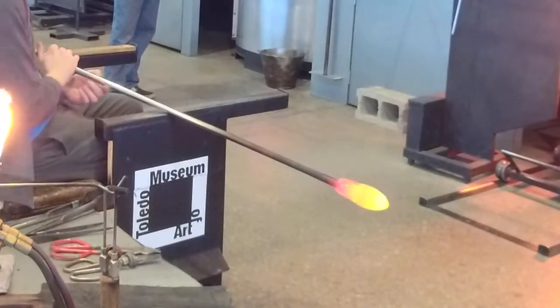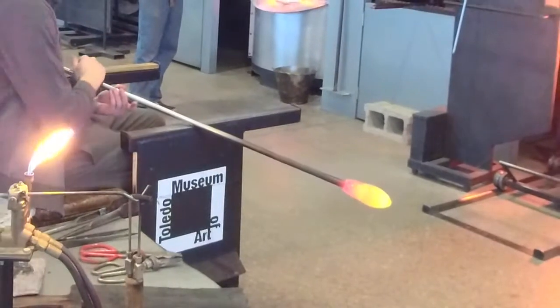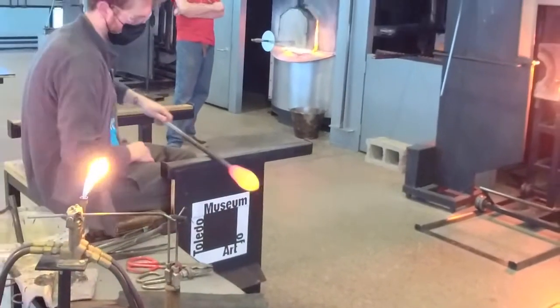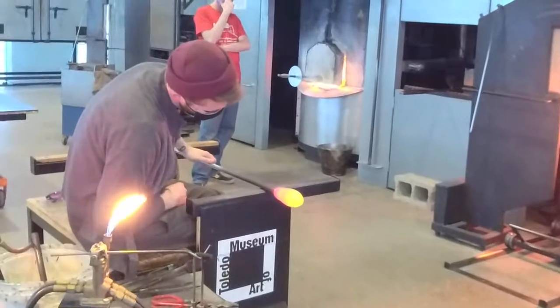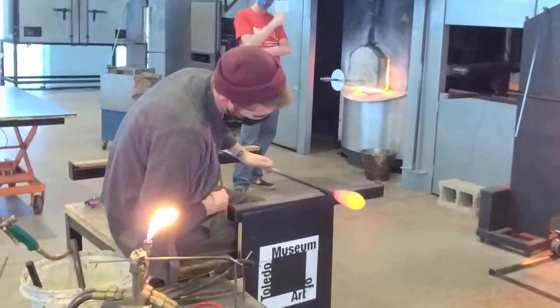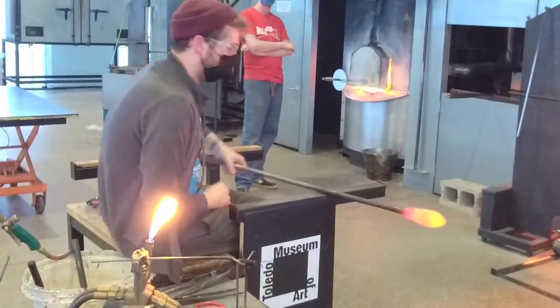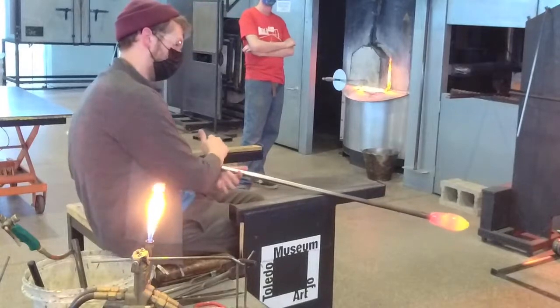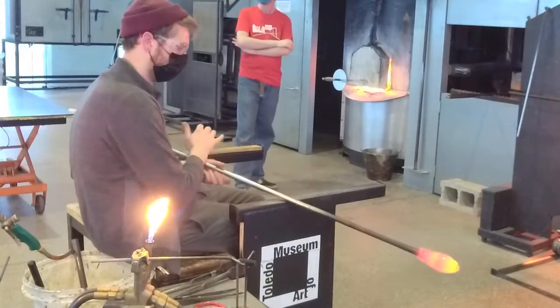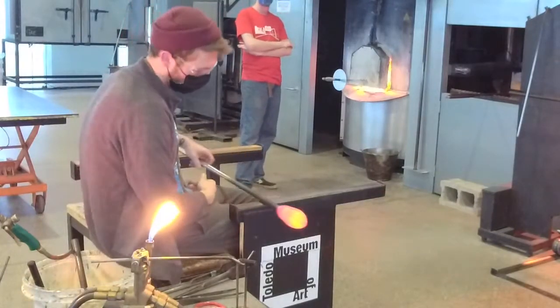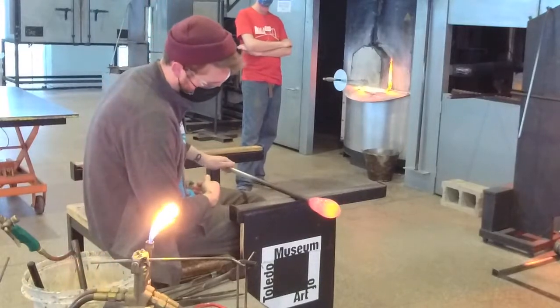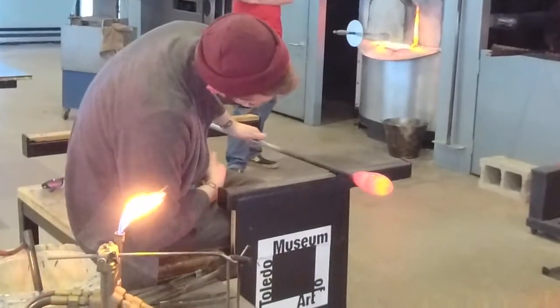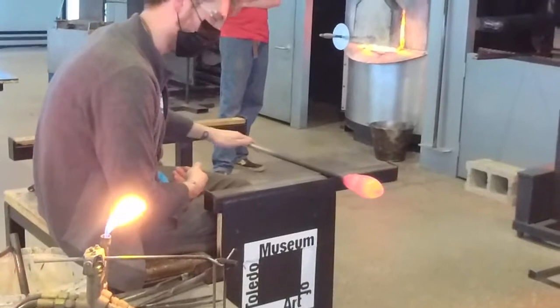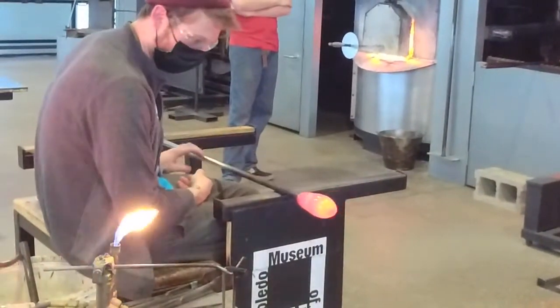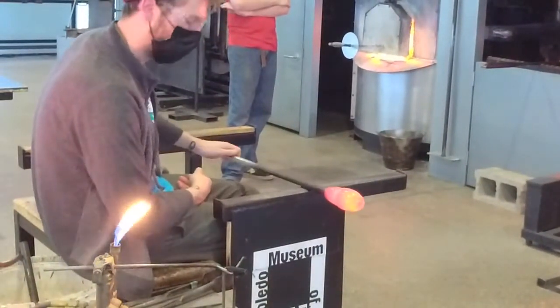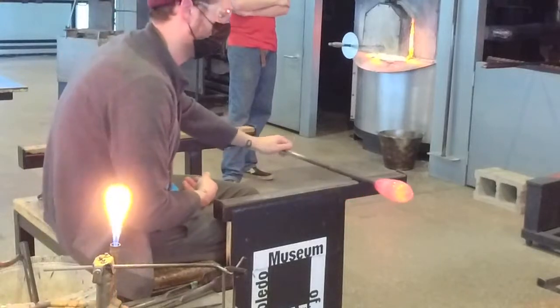You don't want to have any little pockets or dimples in your glass when you go back into the furnace, because glass isn't like water. It's not going to just flow everywhere. It's going to get air bubbles trapped in it if there's any sort of imperfections in the face of your glass. But if you do want bubbles, like if you're making a paperweight, you want to put a whole bunch of little air pockets into your glass, so you're going to have a whole bunch of little dimples that glass can trap those air bubbles into.